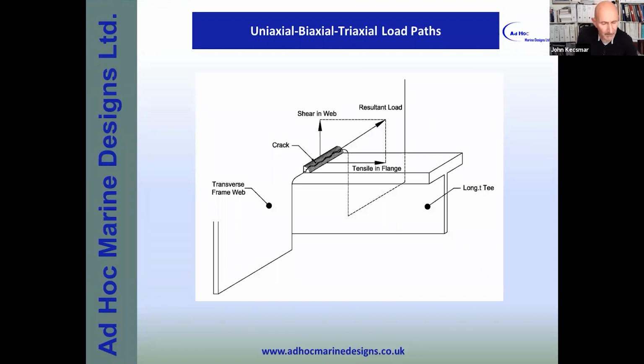However, if we look at this somewhat pictorially, we can see, okay, we have that transfer of the shear, but as the longitudinal is bending, there's also a tensile load in the flange. So suddenly this weld that perhaps was only designed to carry shear is now having shear and tensile and is a biaxial stress raiser. And not only that, the resultant load is quite possibly much greater than was allowed for.